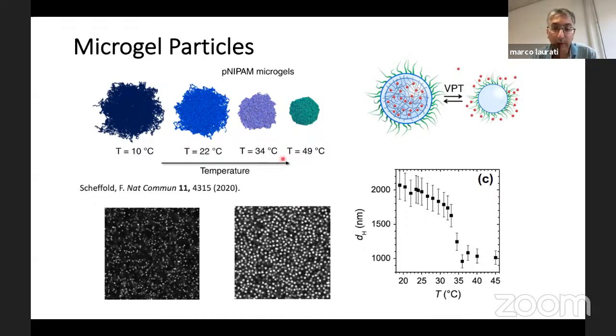So here you see a couple of microscopy pictures of the particles that we were using. So in the swollen state, and then of course, in the deswollen state. And here you can see effectively the measured deswelling transition in the size of the particles as a function of the temperature for our system.